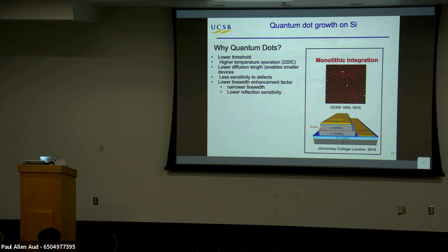But then the real big win is this fact, that with quantum dots, you can get lower line width enhancement factor. And that ends up giving you narrow line width lasers, which is good, but it also reduces your reflection sensitivity dramatically by orders of magnitude, actually.